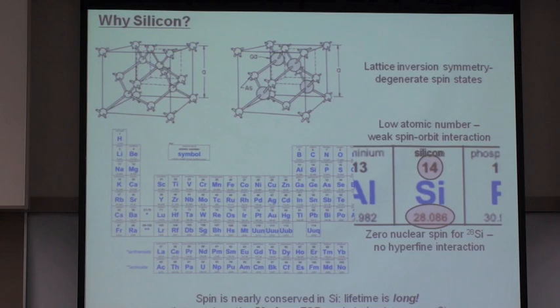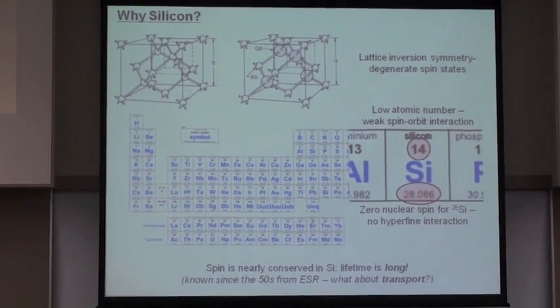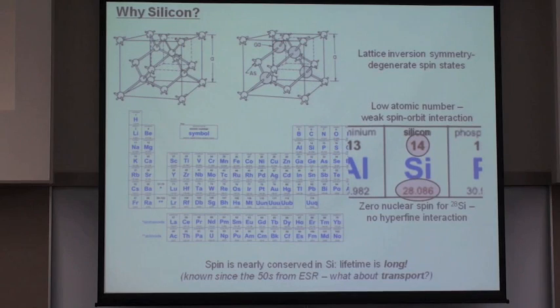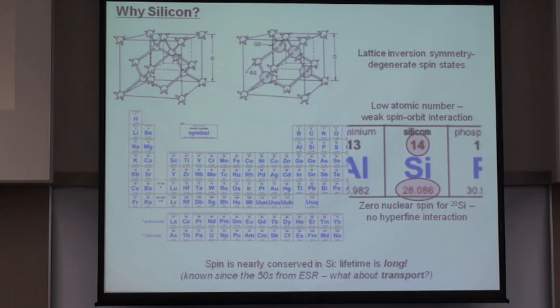The angular momentum associated with orbital motion in the spin-orbit interaction, also due to the fact that at least in naturally abundant silicon, most of the isotopes have no nuclear spin, so the hyperfine interaction is weak. And furthermore, due to a lattice inversion symmetry in the presence of time inversion symmetry, you have degenerate spin states, and so you don't have the same kind of relaxation processes which give rise to short spin lifetimes in, say, compound semiconductors, which are not centrosymmetric.